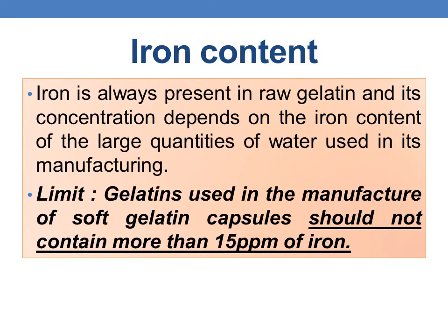Coming to iron content: iron is always an integral part of the raw gelatin and its concentration depends on the iron content of large quantities of water that are used in its manufacturing. The gelatin used in the manufacture of soft gelatin capsules should not contain more than 15 ppm of iron.